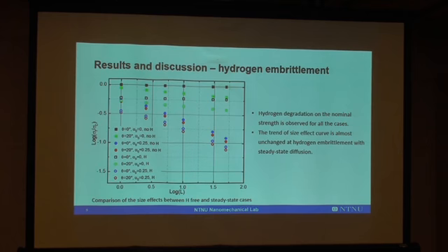So what is the situation in the hydrogen embrittlement case? As aforementioned, this case is divided into two subcases. In the transient diffusion case, hydrogen has to move from the grain boundary step by step to the crack initiation point. That means the hydrogen distribution at failure might be different for different grain sizes, because the distance for hydrogen to travel depends on the grain size.